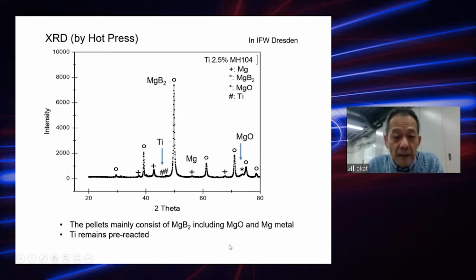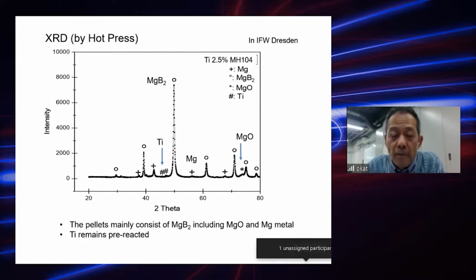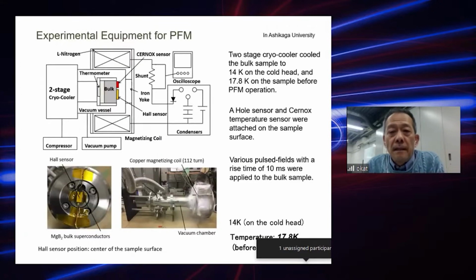This is a view graph of XRD patterns of the hot pressed sample made in IFW Dresden. The pellets mainly consist of MgB2, including MgO and Mg metal. The titanium added to the sample remains unreacted, so it exists as a metal because of the very small amount of addition.